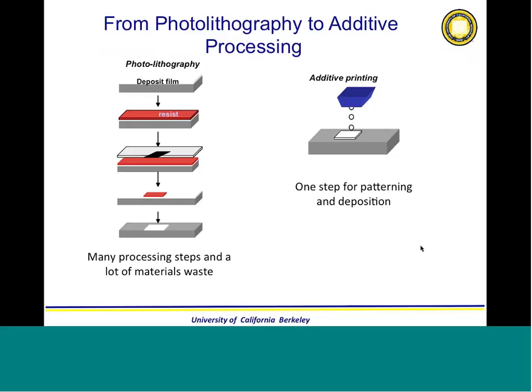It has disadvantages, of course, because with photolithography, you can get really high resolution, very small features, very nice alignment layer to layer in the nanometer scale. In printing, we are in micro scale. So the feature sizes are about 30 microns. The spacing between two features is about 10 microns. The alignment layer to layer is about 5 microns, 1 micron if you have a very good printer. So it's a different idea, and of course, if I try to use printing to do something that photolithography does extremely well, I'm not going to succeed. So it's much better to use printing and different materials on applications where the conventional way of doing things is not coping, such as large area and other things that I hope I'll convince you today.